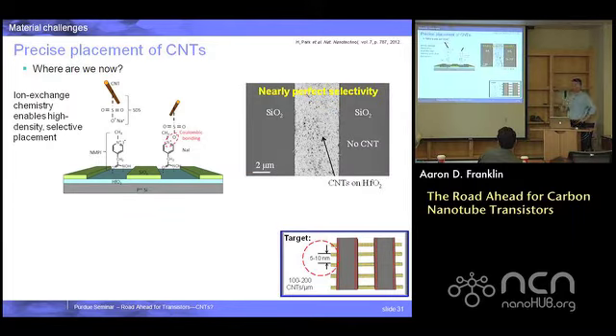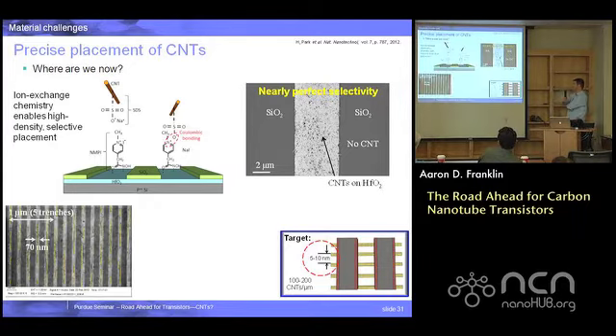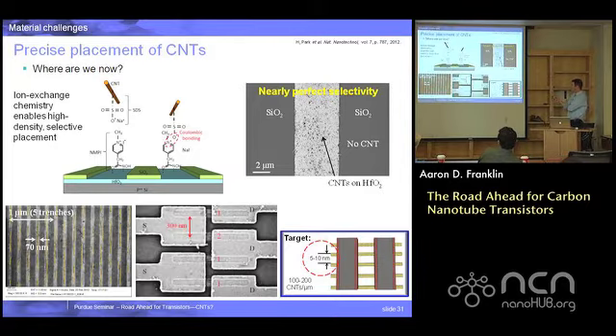The selectivity on this actually is near perfect. It is one of the things that's not a problem with this approach. The nanotubes will just stick where that hafnium oxide and the NMPI is and not on the SiO2. The hard part about it that is still being worked on, and I have two SEMs showing parts of this, this one has some lines added to show you where the tubes are, but that is getting them to be placed close enough together. The smallest that we have in this work is about 100 nanometer pitch that is a really reliable approach, so 10 nanotubes per micron, about an order of magnitude away from where it needs to be, because you start having issues with nanotubes jumping across the trenches.